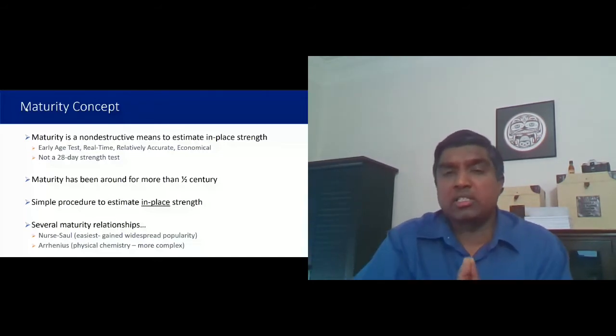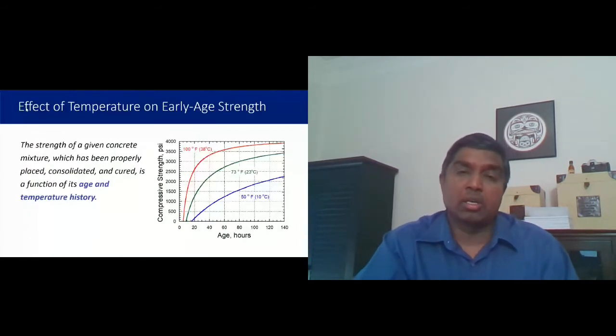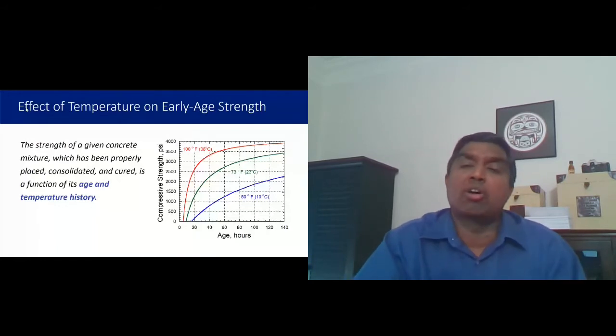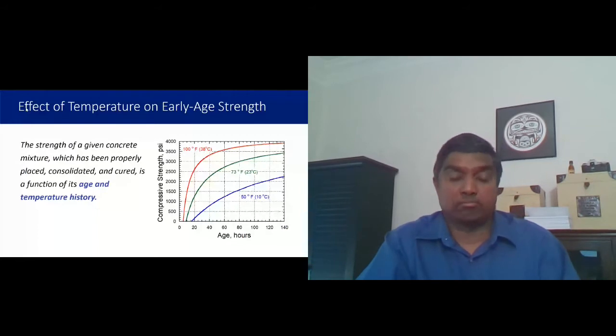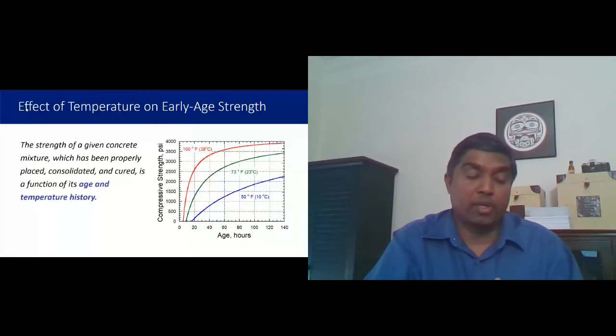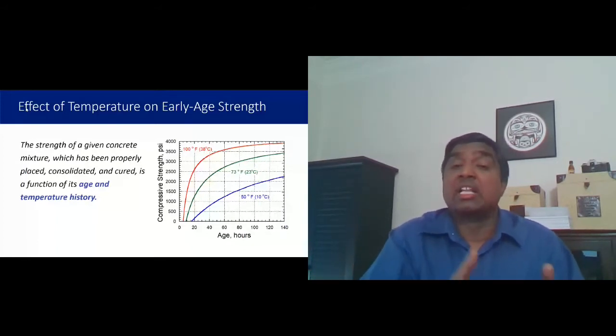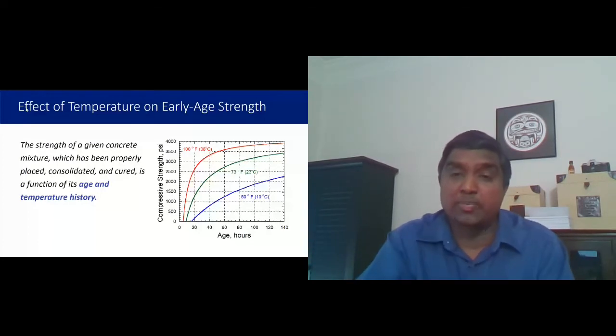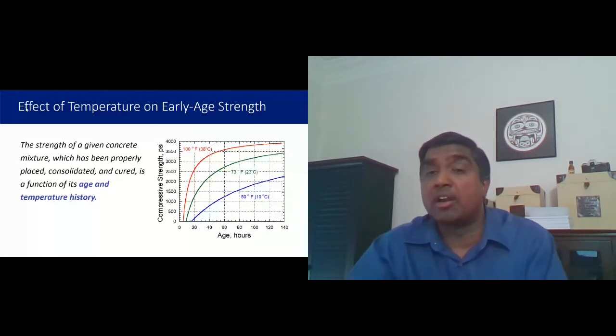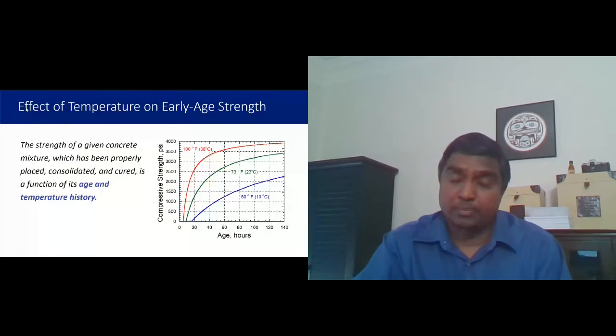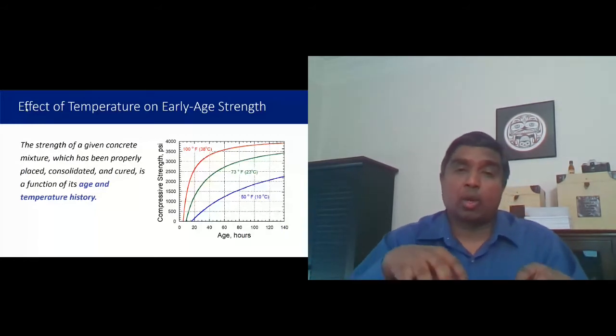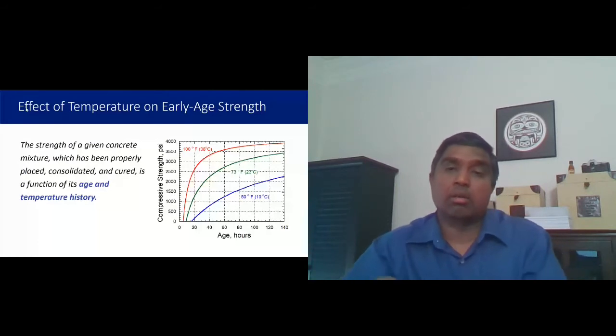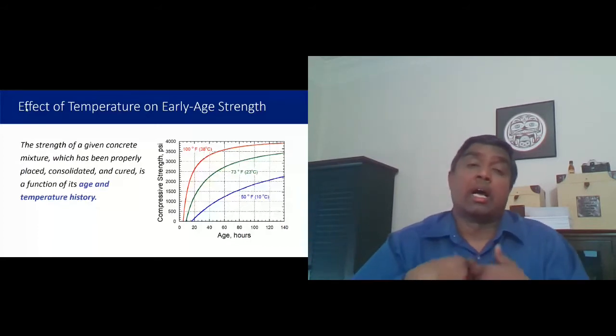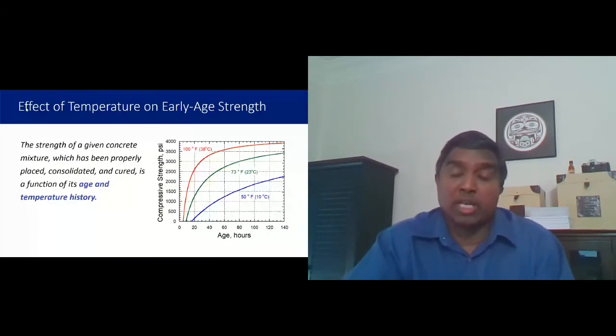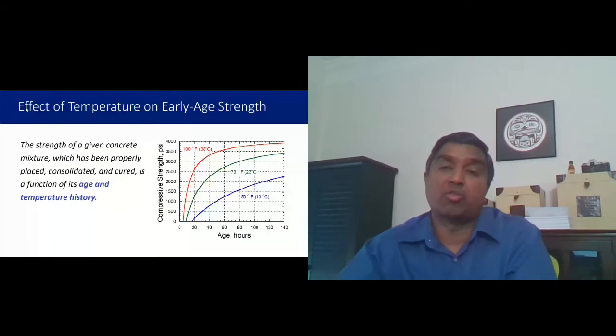Before we jump into maturity, let's first discuss how age and curing temperature impact strength gain. Just based on our experience, we all know that as concrete ages, it gains more strength. Similarly, if you cure concrete at different temperatures, the higher the temperature, the higher the strength gain is. As you can see in this particular graph, the concrete cured at 100 degrees has significantly more strength than the concrete cured at either 73 or 50 degrees F. Now, what maturity really does is it quantifies the impact of both age, which is time, and the curing temperature.